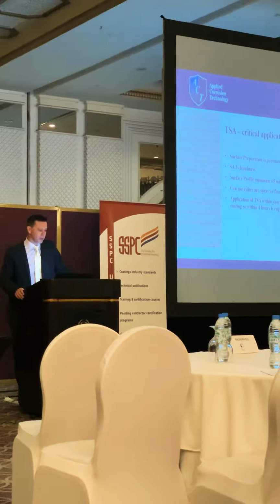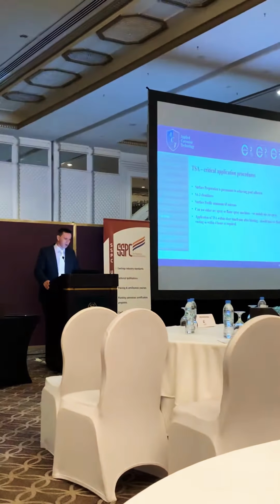Application, surface preparation in TSA is really paramount. It's the key to achieving the right result. And as such, most specifications will call for an SA3, which is a very high level of cleanliness, and a surface profile of 65 microns as a minimum is what we should be aiming for. You can use either arc spray or flame spray machines. The literature in the previous slides is around arc spray, which is the most common that we would find in our market.